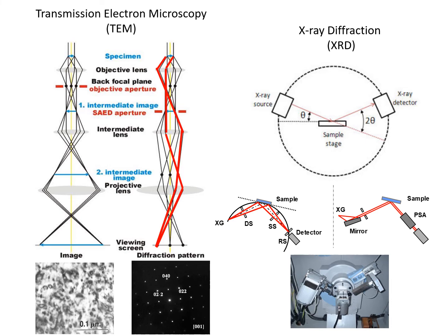And in that situation, one can create different modes of examining a material. In the image mode, we can look directly at the microstructure. We have a real picture of real space, what's going on in the material, albeit in projection. We're shining light or electrons through the material, and we're looking at the projected image. So this may be a bulk sample, and a lot of these defects here may be lying sometimes at different heights within the sample, but we're seeing the projected image here.